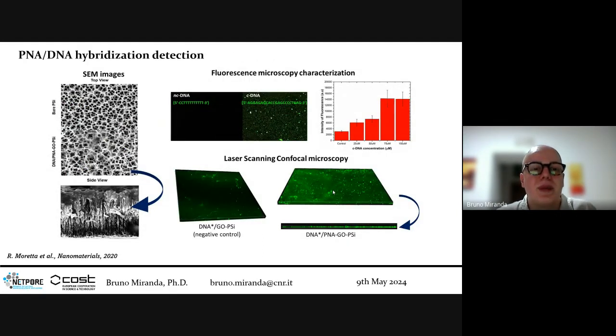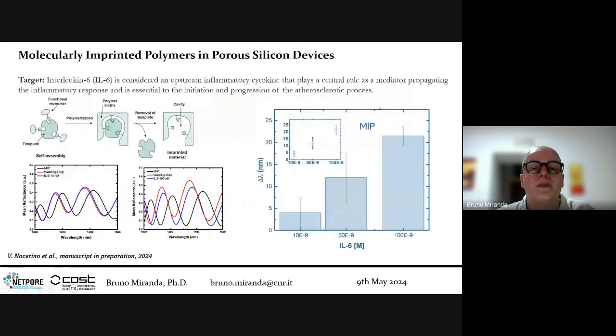These are some SEM images showing the optical porosity of our porous silicon. We also performed controls to verify that non-complementary DNA was not detected under fluorescence microscopy. We labeled the non-complementary and complementary DNA with the same fluorescent dye, and as you can see, in presence of complementary DNA with the PNA, we have strong fluorescence, also working as a function of concentration.